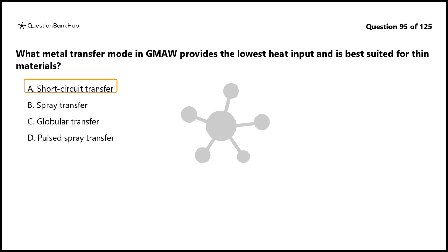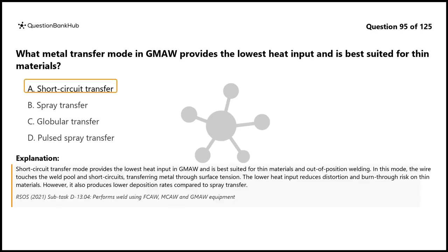Short circuit transfer. Short circuit transfer mode provides the lowest heat input in GMAW and is best suited for thin materials and out-of-position welding. In this mode, the wire touches the weld pool and short circuits, transferring metal through surface tension. The lower heat input reduces distortion and burn-through risk on thin materials. However, it also produces lower deposition rates compared to spray transfer.